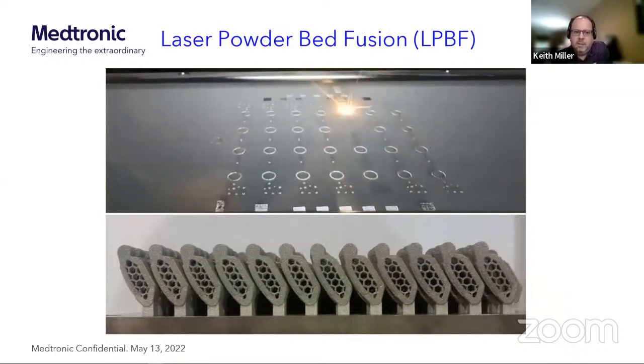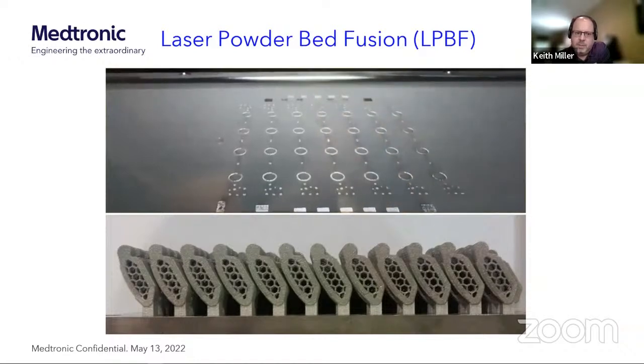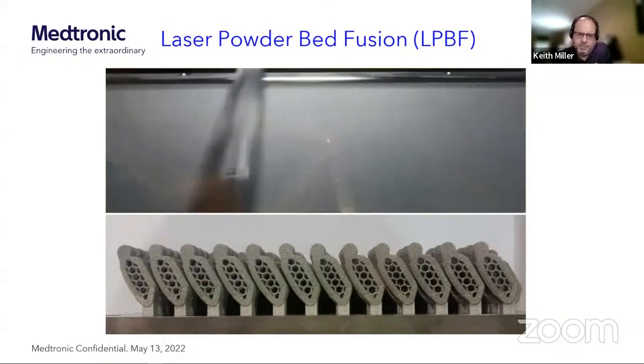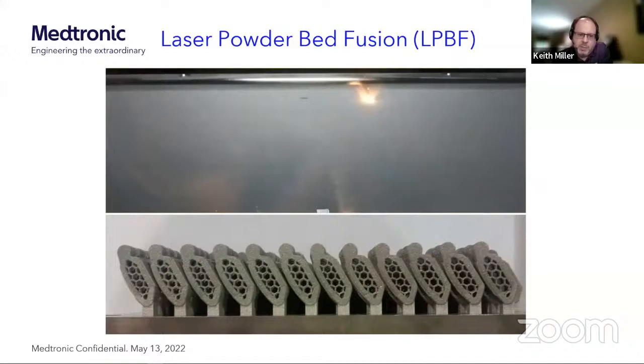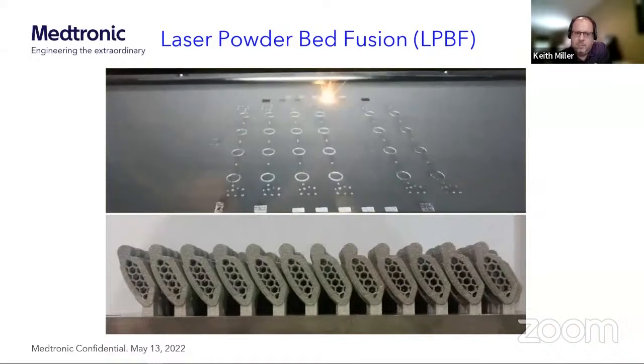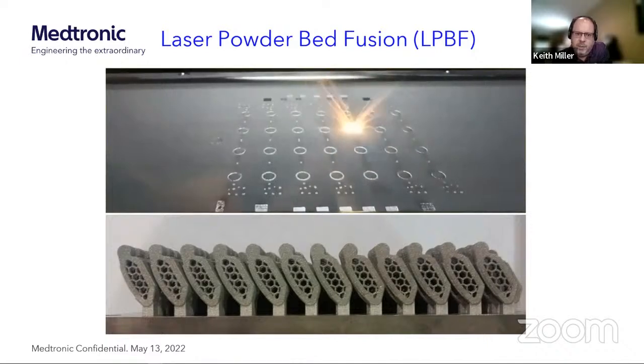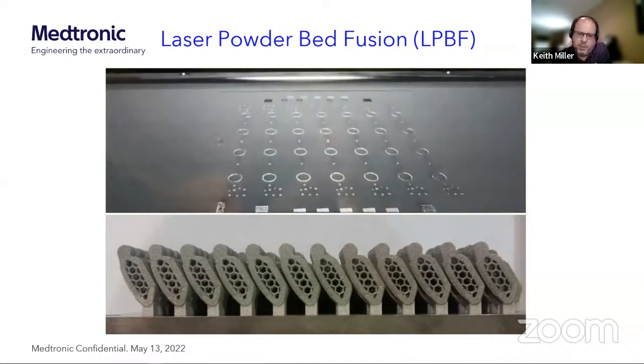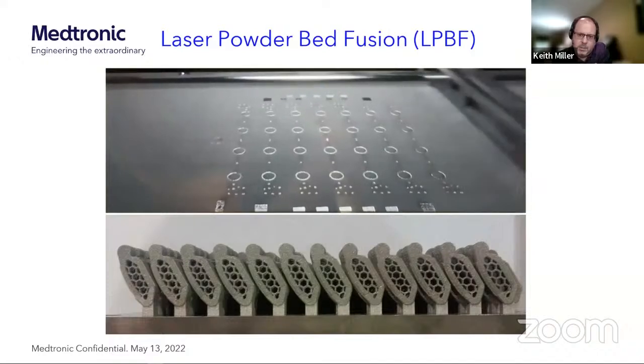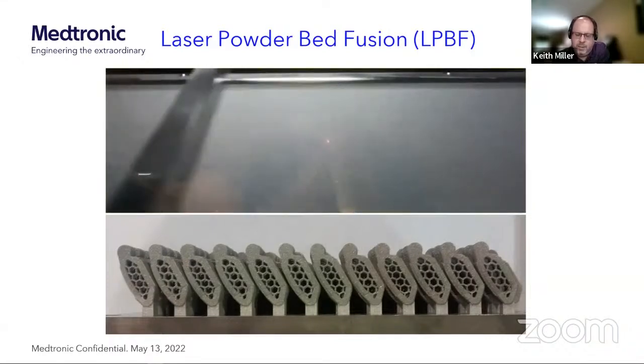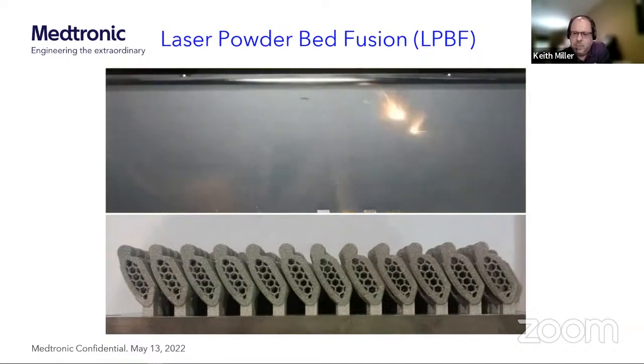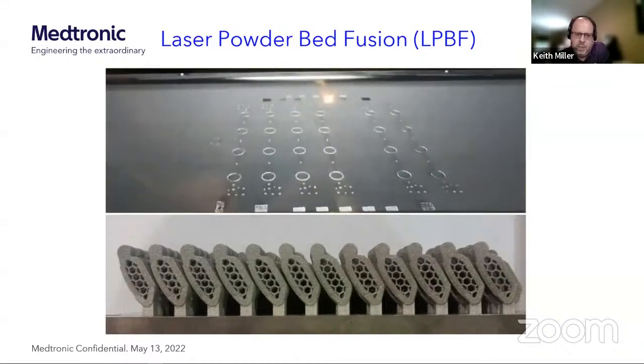So, the FDA calls the 3D printing that we use in our devices laser powder bed fusion. Many companies have their own trade names for it, but I like to use the FDA definition of it. The way it works is basically you have a layer of titanium powder on a build plate, and a laser comes back and melts that powder into a solid geometry. Then we have what we call a recoater, basically spreading another layer of titanium powder on top of that. Then the laser comes back and does it again. So multiple layers, and you end up with solid geometry in the end with this layer-wise process.